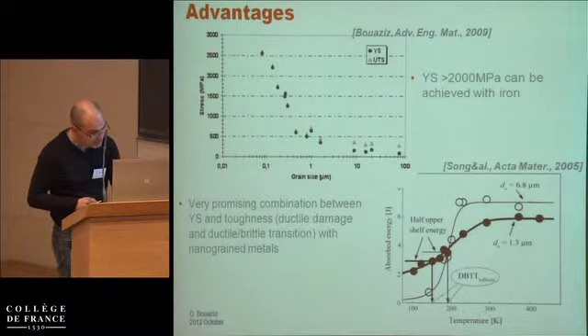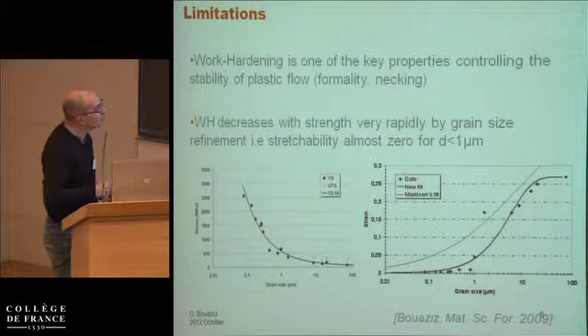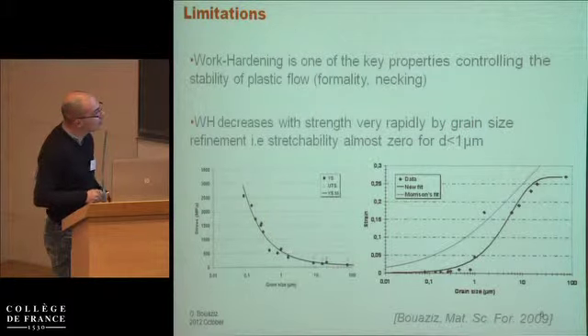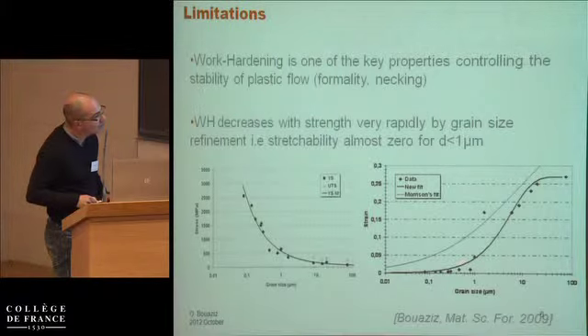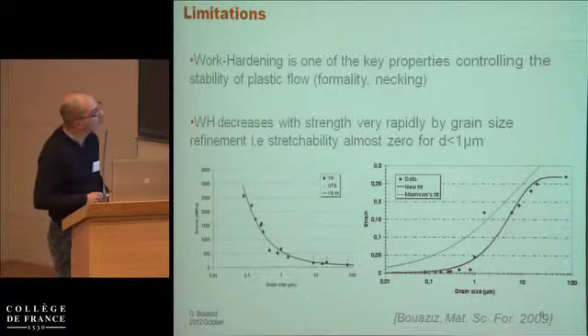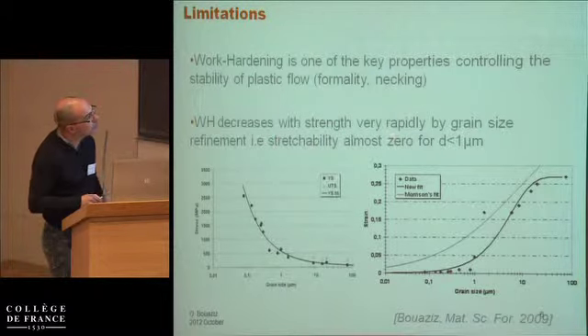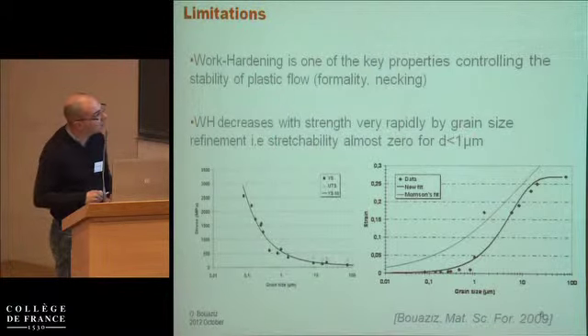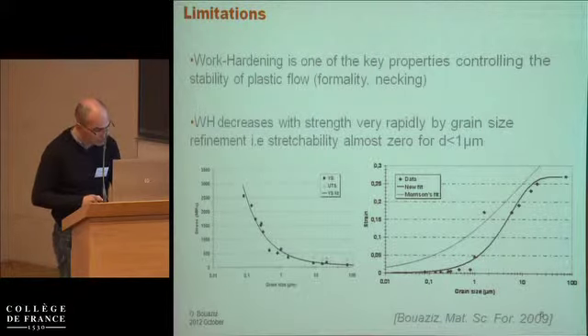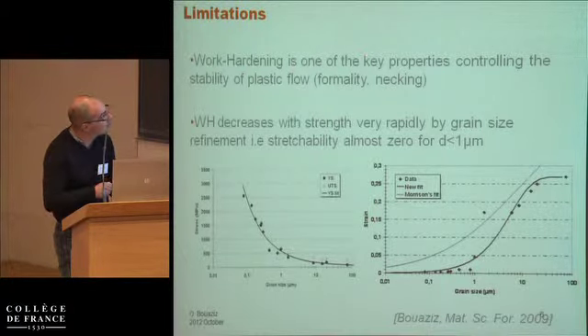But there is a limitation. At the same time as the increase of yield strength, the uniform elongation decreases a lot, and it even goes to zero for grain sizes lower than 1 micron. Work hardening decreases very rapidly with strength by grain size refinement, and in another sense, stretchability is almost zero for grain sizes lower than 1 micron. This is a strong limitation because work hardening controls the plastic flow.